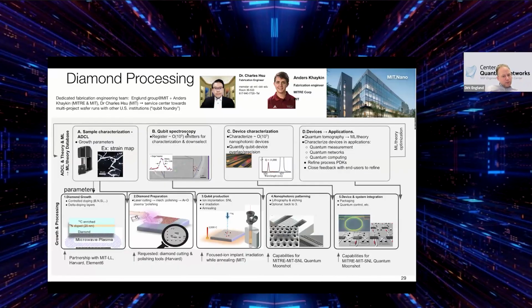Now, fabricating these devices from these kinds of diamond substrates is a difficult process, and a lot of unknowns remain there. As you see, from the properties of the emitters, we're not good enough yet. But here I just give you a sense of what this entails. One way is to first you get a diamond. Oftentimes these are grown by chemical vapor deposition. You do low temperature microscopy. You do spectroscopy on the quantum emitters. Here's an emitter, here's another emitter. You look at the line widths of these, and then you can fabricate structures in the clean room out of them.